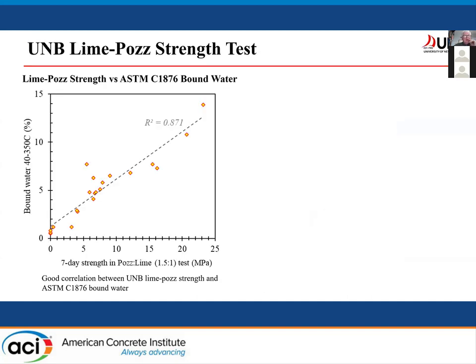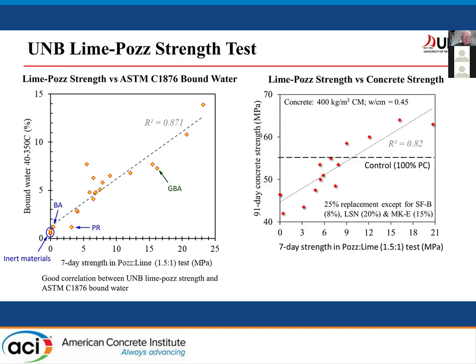Now, if you compare the lime pozzolan test that we're just talking about to this bound water test that's in the new standard, you can see that the inert materials, which would include the unground bottom ash, BA, have very low bound water, very low strength. The ground bottom ash has very high strength and high bound water. So it shows the impact of grinding the material.